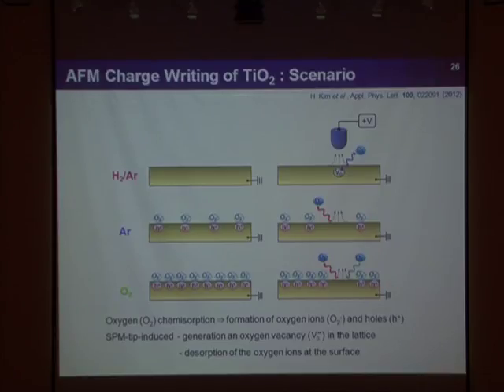From this result, we can see that it's really hard to compare AFM measurements with real MIM structures, because there is a big difference, and the ambient is really important. I showed you that these three different cases can be obtained to control the environment. But if you carry out a similar experiment at just atmospheric pressure, there is a large change in water or humidity level, so everything becomes quite complicated. We really should be very careful to explain experimental results. That's an important message.